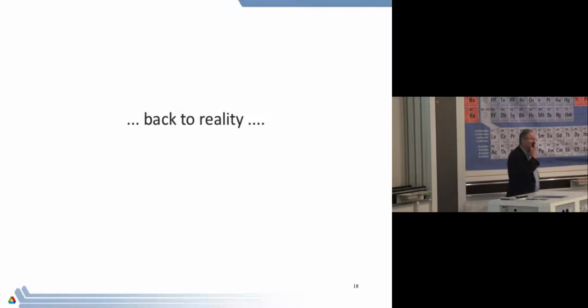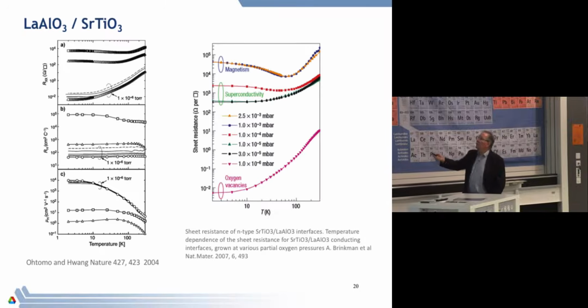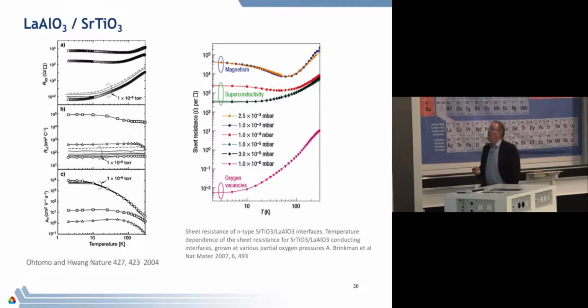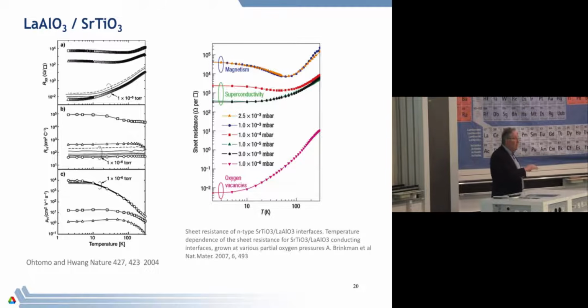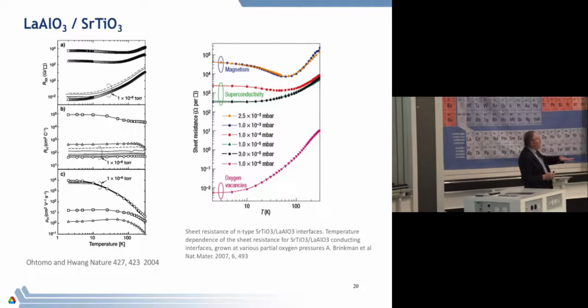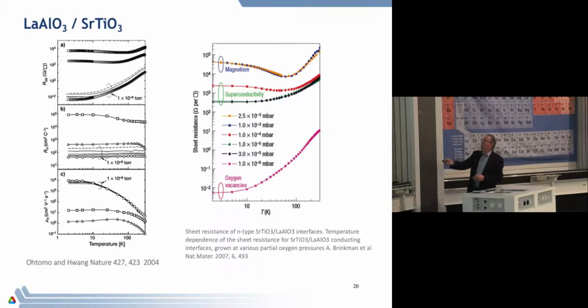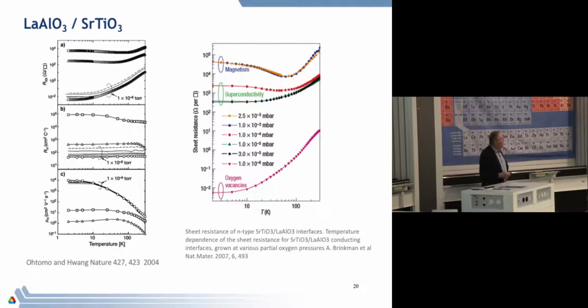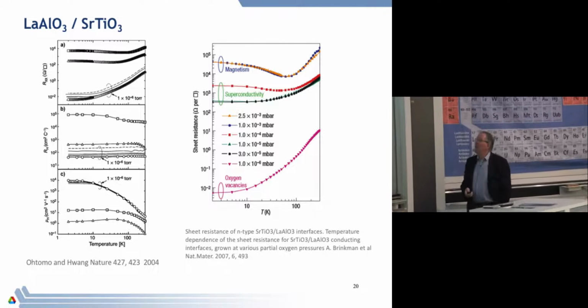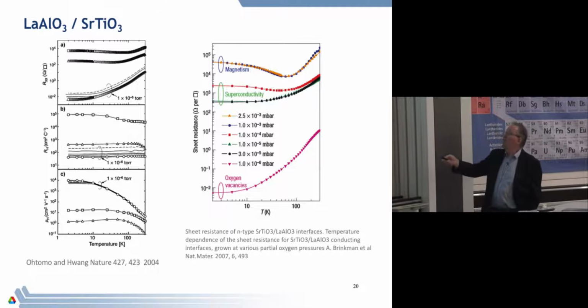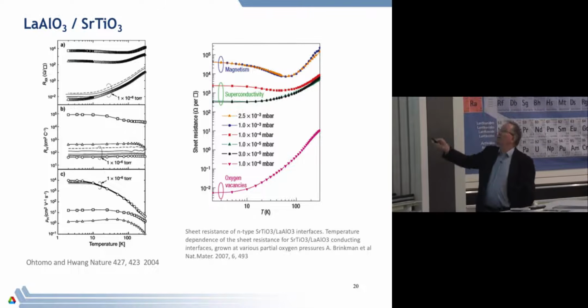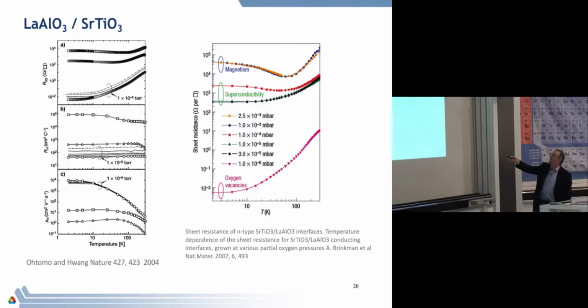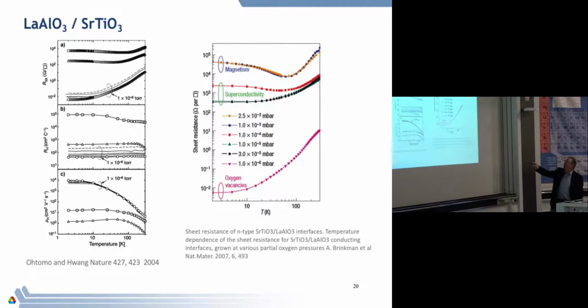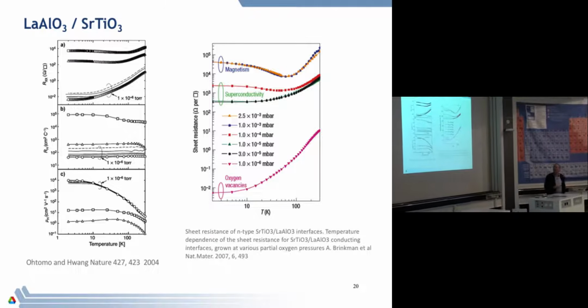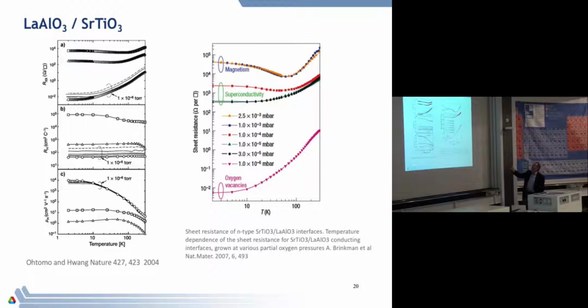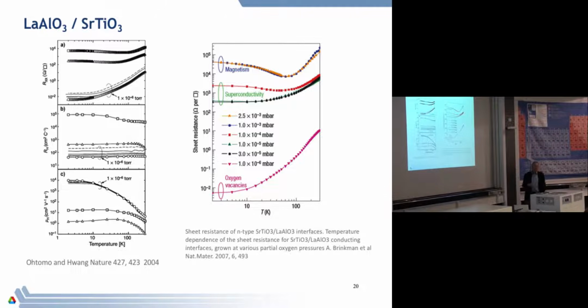But back to reality. So what actually happens, and maybe let's just focus on the right-hand side here, when you make this material, what you can do is measure the conductivity of the electrons at one of those interfaces. And this is resistance versus temperature. Depending on how you grow the surface, you discover you get very different answers. Sometimes you get a really good metal. Sometimes you get something which is a much worse metal, but still metallic, and in fact, at low temperatures, superconducts. And sometimes you get something which is a much worse metal, but then shows magnetism in here.